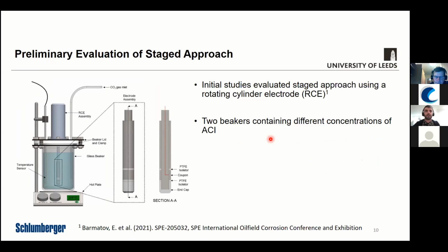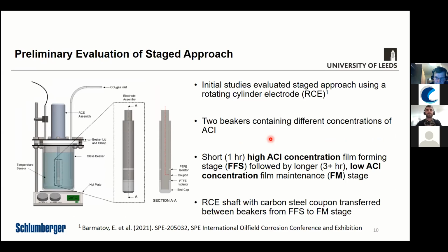So the preliminary way to establish whether or not this was going to be an effective technique was done by Evgeny and Trevor at Schlumberger, essentially using a rotating cylinder electrode and using 2 different beakers containing the different concentrations of corrosion inhibitor. So essentially what they would do is mount the carbon steel coupon on the rotating cylinder electrode shaft, immerse that in a high inhibitor concentration solution for the film forming stage. Complete that for 1 hour, and then move the RCE into another beaker with a lower concentration of inhibitor. And that period, which would be the film maintenance stage, would last for a significantly longer period. And the corrosion rates would be evaluated over that time period to see whether or not that influenced the inhibition efficiency over the duration of the matrix acidizing injection period.